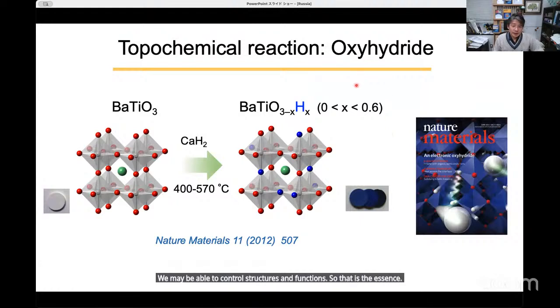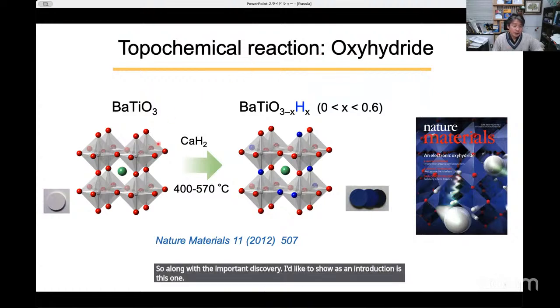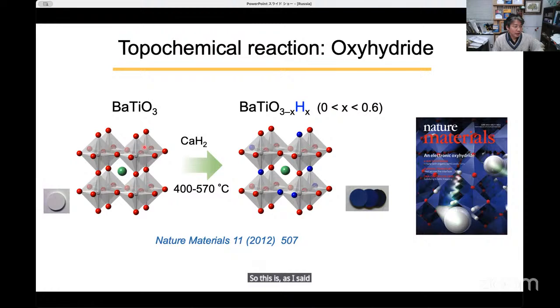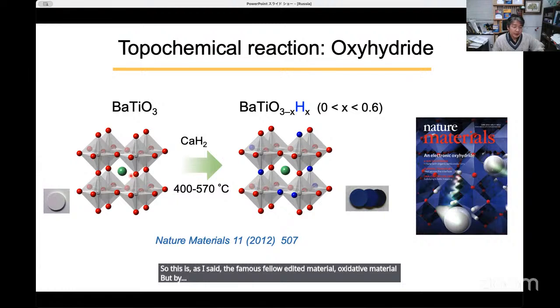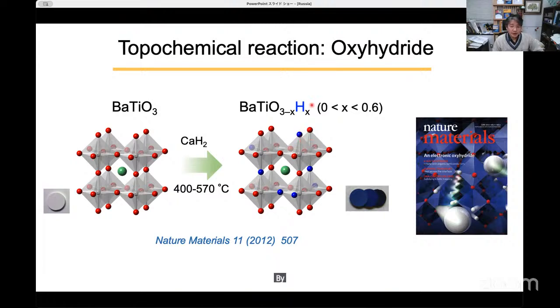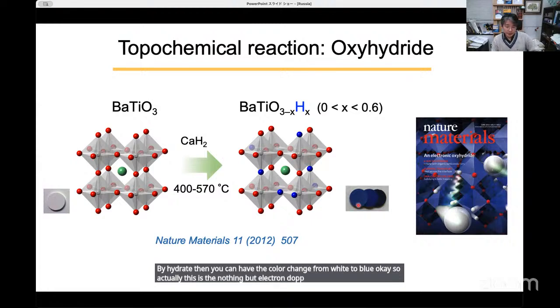One of the important discoveries I'd like to show as an introduction is this one. This is, as I said, the famous ferroelectric oxide material. By reacting this powder sample with calcium hydride at this temperature in vacuum, we are able to partly replace some of the oxygen ligands, these red guys, by hydride ligands. Then you have a color change from white to blue. This is nothing but electron doping, so this shows metallic behavior.